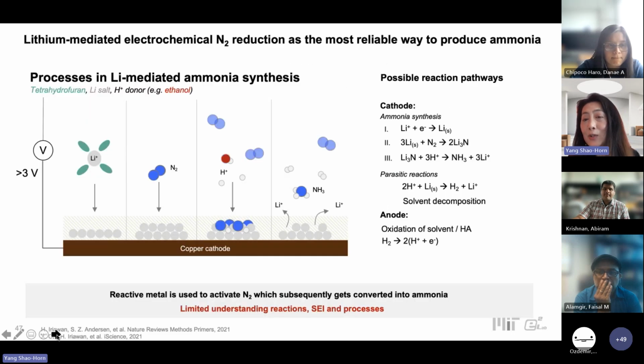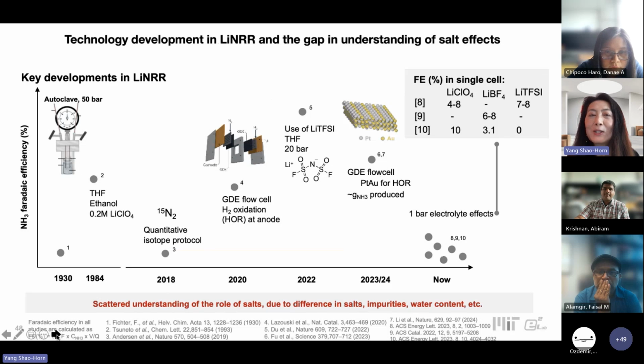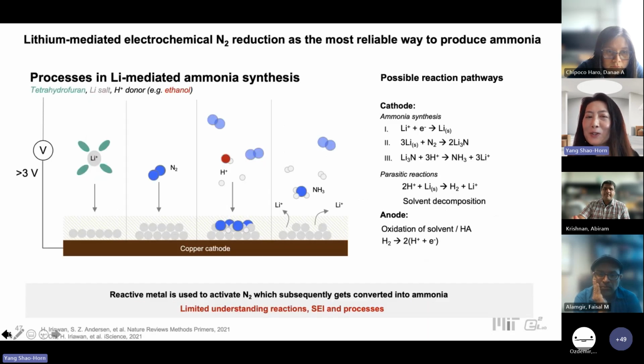Not only is this really important, I just want to end this talk by saying that there are a large number of research groups also utilizing lithium to mediate the electrochemical reduction of nitrogen, right? So essentially we use lithium as a reducing agent to bind and dissociate nitrogen, and then once we have lithium nitride, we have a protic source, let's say ethanol, and on the surface we can generate ammonia.